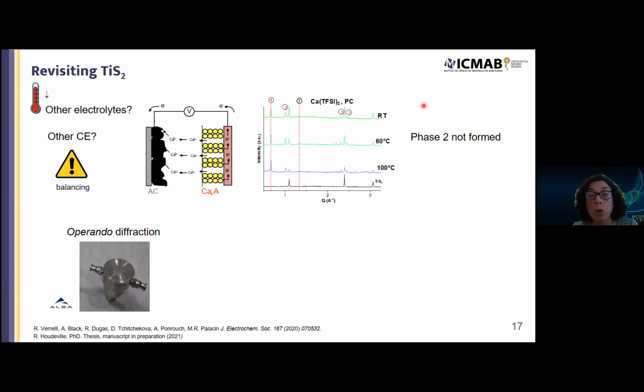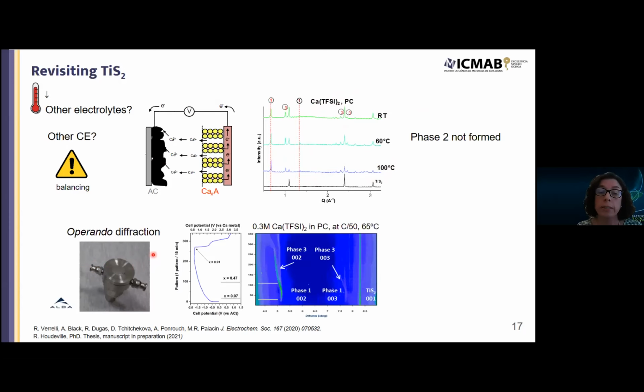Then we were following this intercalation mechanism by operando diffraction, and this was done at ALBA. This is an operando cell, which enables circulation of a fluid to increase temperature. And this is what we got at 65 degrees C, and we are still investigating this, because the redox mechanism seems to be much more complex than what we have thought. And in fact, the position of those peaks seems to be evolving in the course of cycling. So the mechanism is something that we still need to understand better.